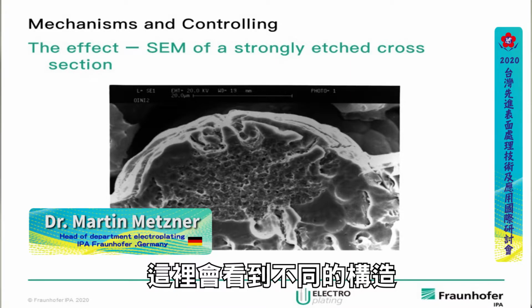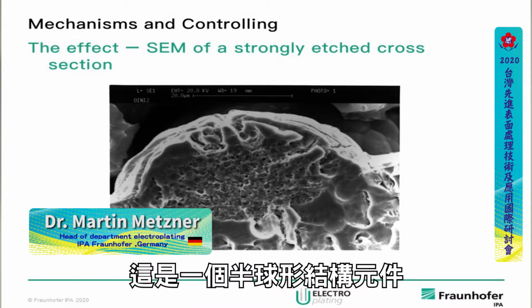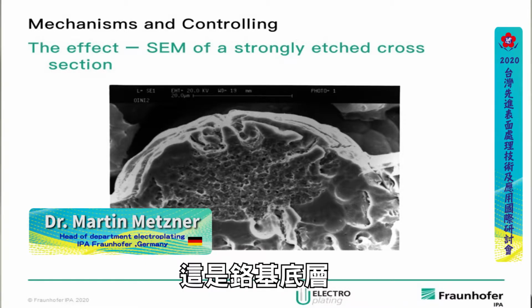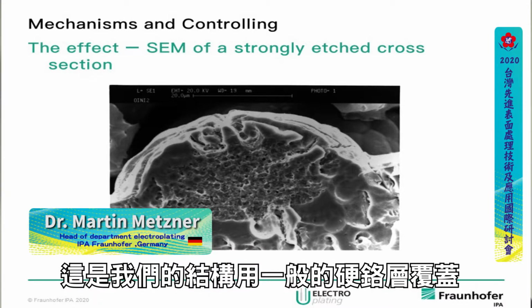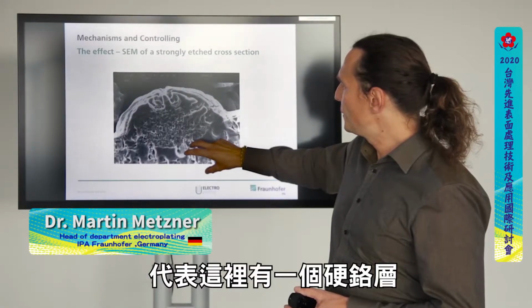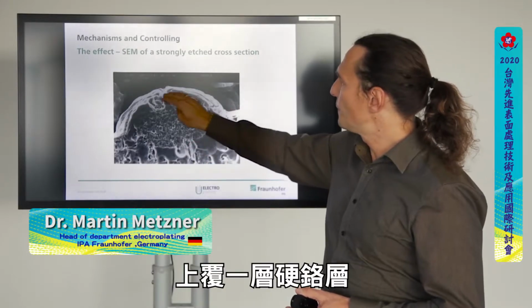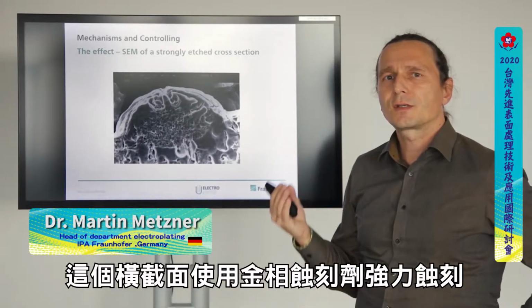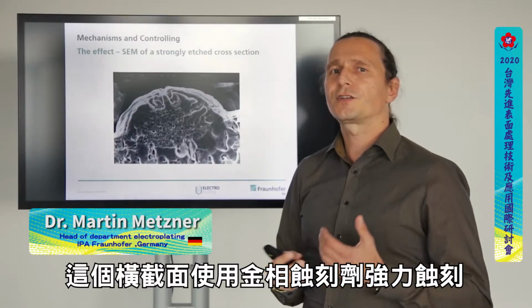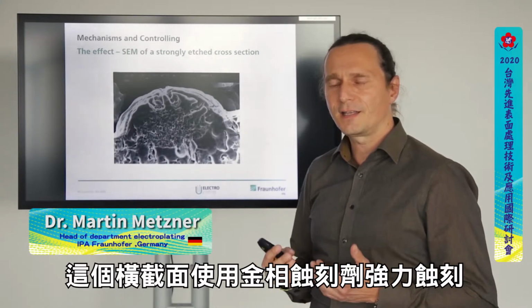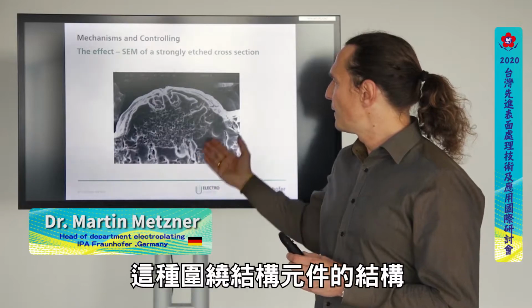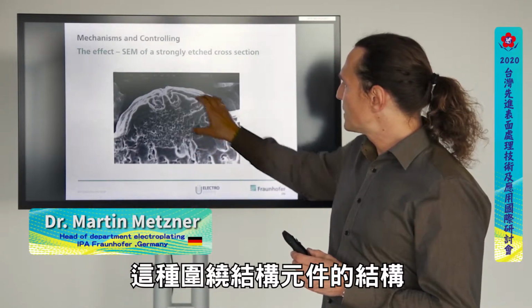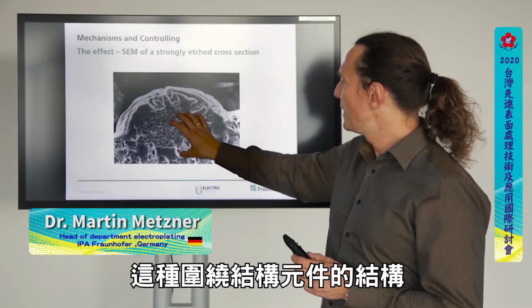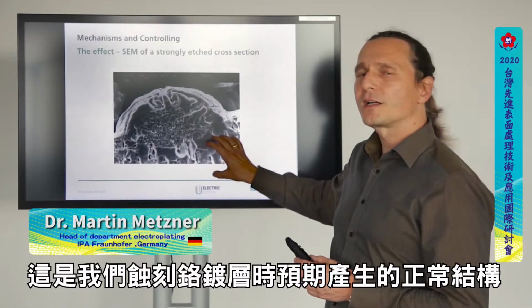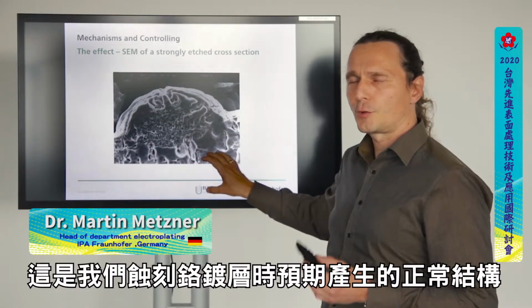You see different things here. This is really a hemispheric structure element, so this is a base chromium we have here. This is our structure, and we cover the whole thing with a normal hard chromium layer. We've got a covering hard chromium layer, and this cross-section is now very strongly etched with the metallographic etching agents. Very strong etched, and what you see here, this structure surrounding the structure element, this is the normal structure that we would wait for when we etch a chromium layer.